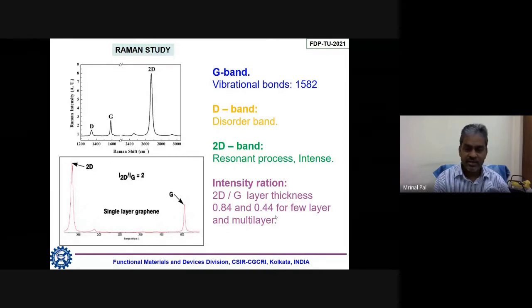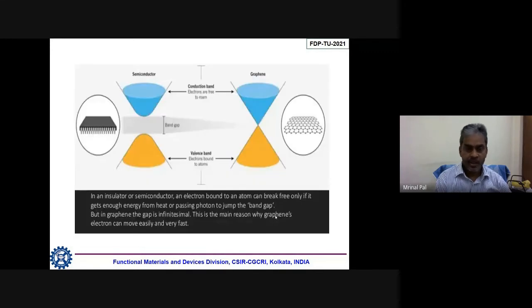I hope I am able to convey the message to you why Raman study is important and what the 3 important bands of this Raman study are, D, G and 2D bands, and what their ratio implies. So this is the band structure. As I have mentioned, in case of an insulator or semiconductor, this is the valence band and this top one is the conduction band. So this is a kind of semiconductor or insulator and this is the gap. But for graphene, again I must say that the valence band and conduction band meet at a particular point only. This is the K point, and because of this meeting, graphene is a semi-metal kind of thing. And as they have met, we call this a zero band gap semiconductor.